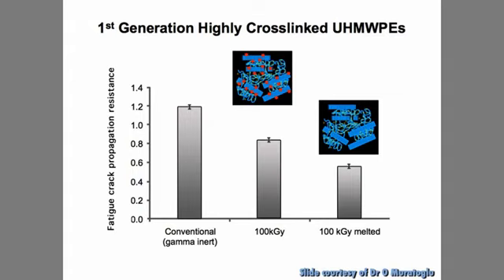The next problem you have is that cross-linking and remelting to get rid of free radicals seriously degrades the mechanical properties of polyethylene. And you can see with 100 kilogray radiation, cross-linking and remelting, there is a 50% reduction in fatigue crack propagation resistance in cross-linked polyethylene compared to conventional polyethylene that has been used for many years. Of course, the advantage of the cross-linked polyethylene is that we have much better wear resistance. The advantage of the conventional is we have far better mechanical properties.